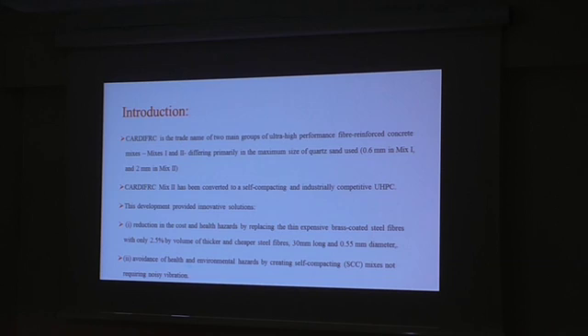CARDIFRC Mix II has been developed to self-compacting and industrially competitive ultra-high performance concrete. This development provided innovative solutions. One solution is a reduction in cost by replacing the thin, expensive, brass-coated steel fibers with only 2.5% by volume of cheaper steel fiber, 30mm long and 0.55mm diameter. The second solution is avoidance of health and environmental hazards by creating self-compacting concrete not requiring noisy vibration.